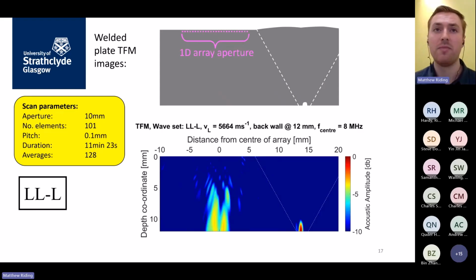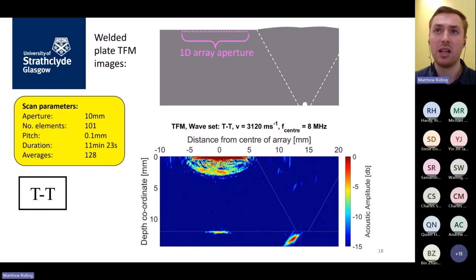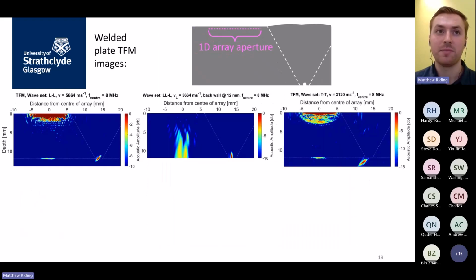We're able to see it with different views. So this is a self-tandem imaging mode, where we're able to see the defect at a nice upright orientation, and with different wave modes. Laser ultrasound is a highly multimodal ultrasonic source, and so we generate all of these images from the single data set, from a single scan. So you get lots of different views of the defect.